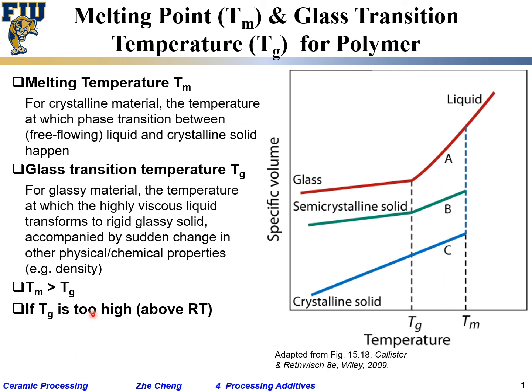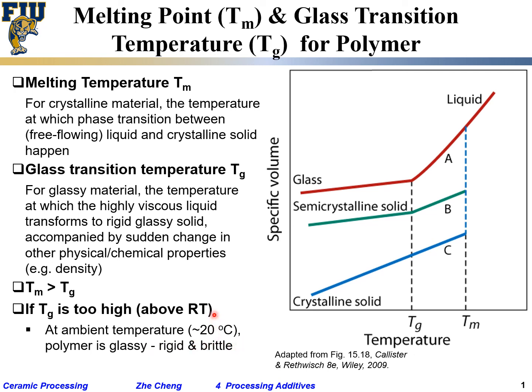If the Tg is too high — much higher than room temperature — then your binder polymer in the ceramic paste behaves like a glass at room temperature. At room temperature you are in the glassy region, so you cannot easily shape it: apply stress and your polymer fractures. You cannot plastically shape it. This means you either have to choose a different binder, or add a so-called plasticizer to reduce the Tg and make the polymer more plastic and softer.